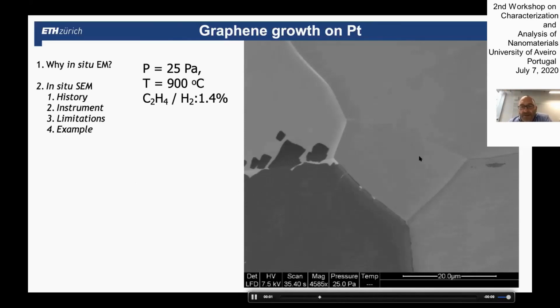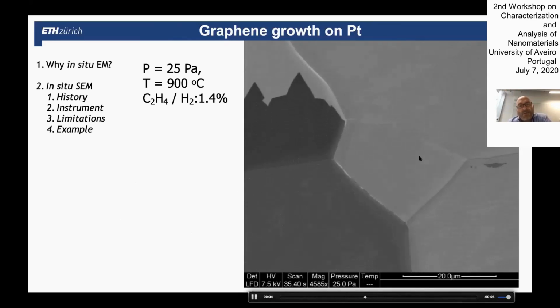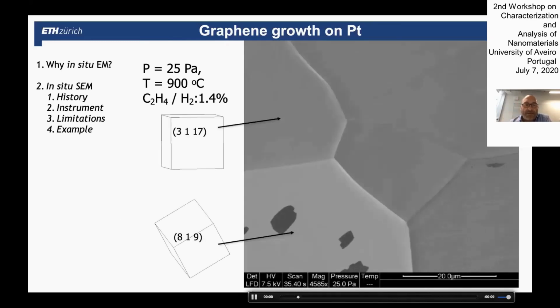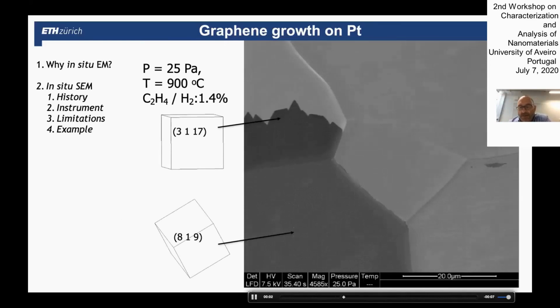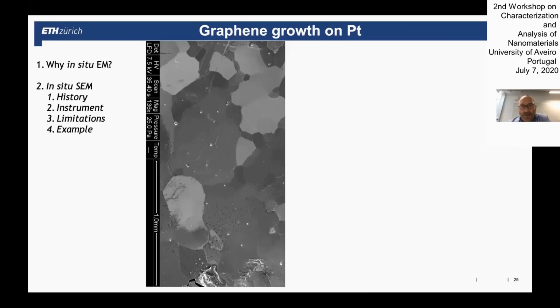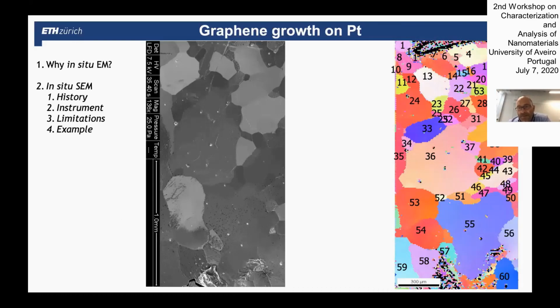So we can in situ, in real time, judge which surface of platinum has the highest catalytic activity for graphene growth. And you can then, with electron backscattering mapping, assign these orientations of the different grains, and you can then plot over a large area activity structure correlations.